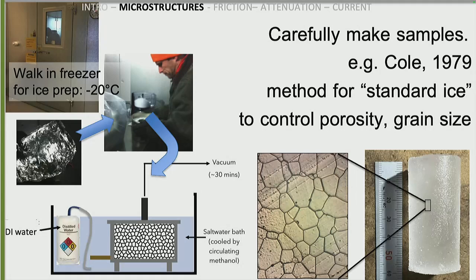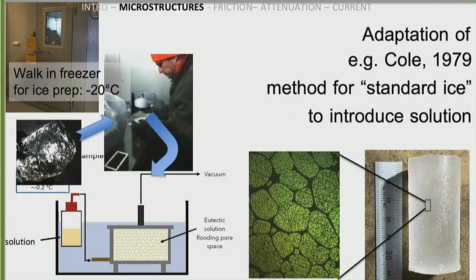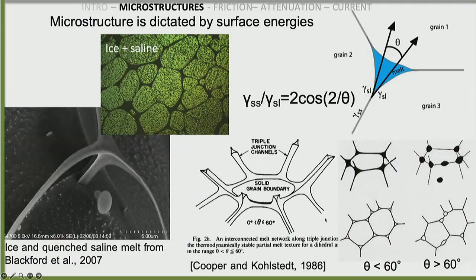And to now add the partial melt, we do all those same first steps, pull the vacuum, but instead of liquid water, we add the solution at that stage. And then what we get is pure ice grains, and then this distributed melt phase throughout. And what is the structure of that melt phase? Well, that is dictated by surface energies, so relative solid-solid surface energies and solid-liquid energies.